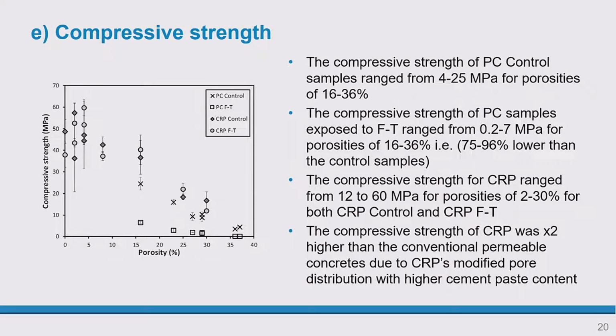The final comparison was the compressive strength. For the conventional systems, it ranged from 4 to 25 megapascals for porosities of 16 to 36%. That's when they are not exposed to freeze-thaw. And when they were exposed to freeze-thaw, it reduced by 75 to 96%. Whereas in the case of CRP, the compressive strength still ranged from 12 to 60 megapascals for the different porosities, irrespective of whether it was a control sample or a freeze-thaw sample, which was very promising for us to see.